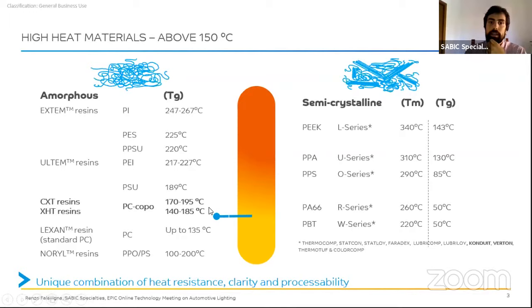So these will meet high temperature requirements, for example, for the components very close to the heat dissipation of the LED lights. And as we know, automotive lighting are a kind of closed environment where the temperatures can rise quite a bit. The difference between the two technologies is that XHT is mainly non-transparent, opaque, while CXT is a fully transparent copolymer, natural color. This is what we can offer from the amorphous side. From the semi-crystalline side, as I mentioned, we can produce tailor-made compounds based on all the resins available on the market. So let me mention just a couple.